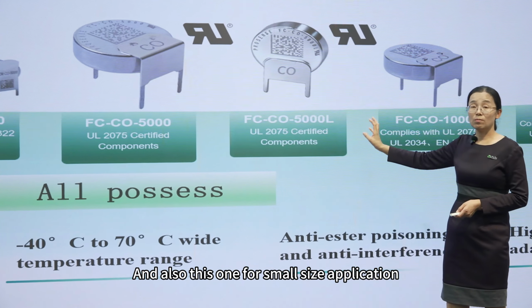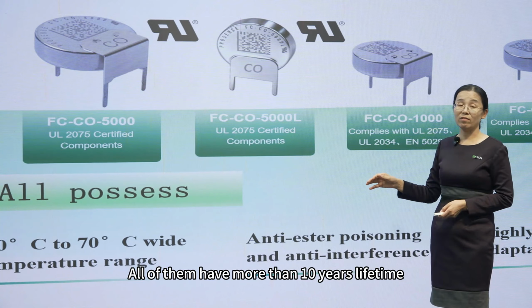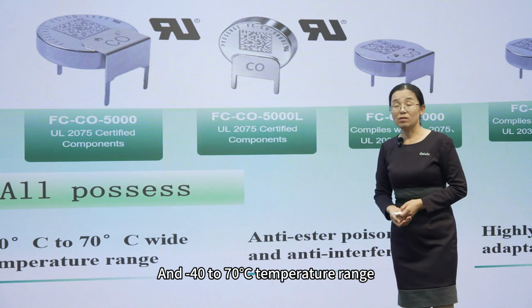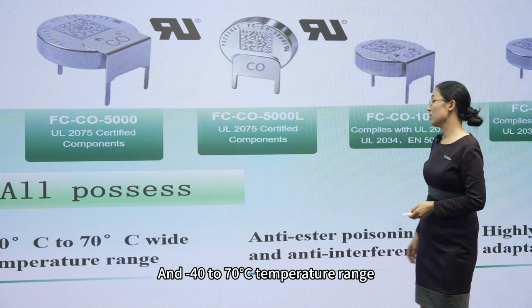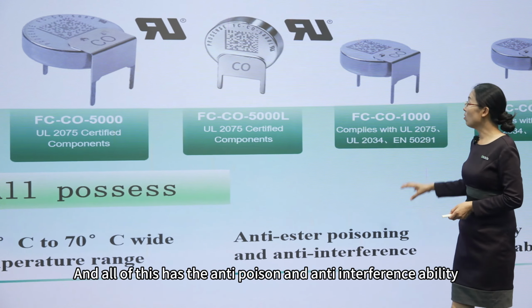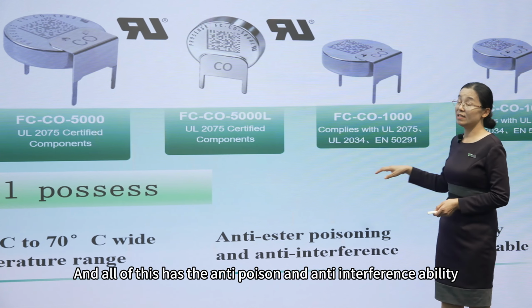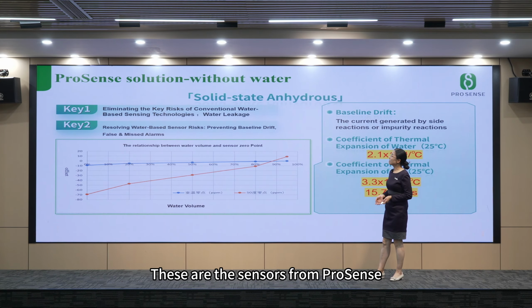And these are the CO sensor family of ProSense. We have the UL recognized battery type and also the coin type, and also this one for small size application. All of them have more than 10 years lifetime and a minus 40 to 70 degrees centigrade temperature range. And all of them have anti-poison and anti-interference ability. They are widely used for the BESS, portable generator, and also for residential and commercial alarms. These are the sensors from ProSense.